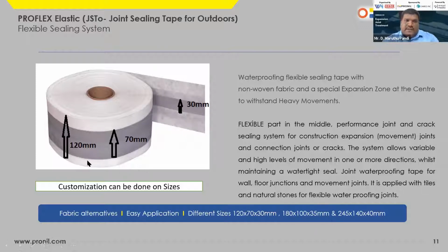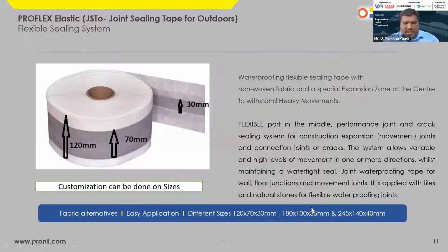The total width is 180, 100 is the TPE coating, and 35 is the flexible zone. And it comes in a bigger size also, 245 by 140 by 40 mm. This product is called the joint sealing tape outdoor, and can be used in some of the precast slabs also, some of the precast movement slabs, where now we put normal sealants like polysulfide or polyurethane sealants. In those areas we can use these tapes also to withstand movements and water tightness.